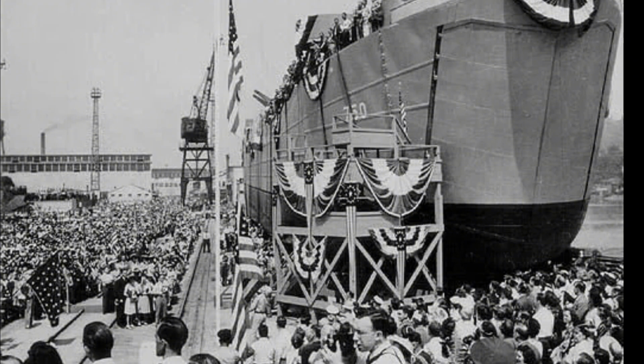Welded construction eliminated those barriers. A continuous weld created a metallurgical bond, essentially making multiple plates into a single continuous structure. The efficiency was obvious. Welding was faster than riveting, required fewer workers, and created lighter structures without the added weight of overlapping plates and thousands of rivets. But the vulnerability was equally clear. A crack in welded structure could propagate continuously across joints that would have stopped it in riveted construction.